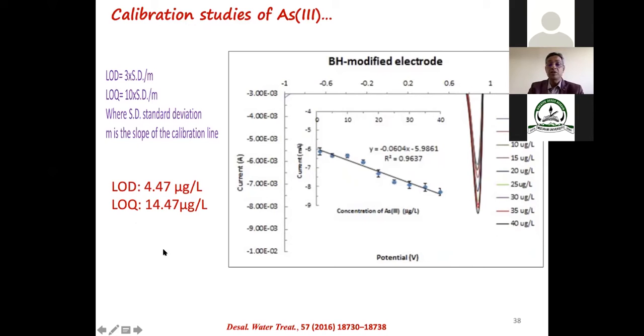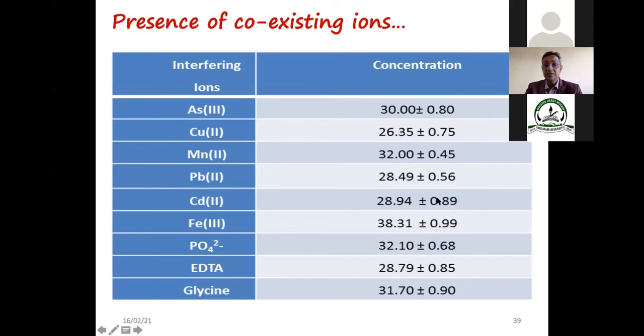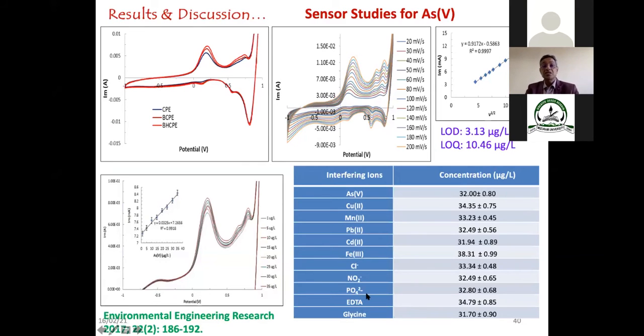The LOQ, limit of quantification, is 10 times SD by M, so 14.47. And for the other existing ions, we observed that most of them do not affect the measurement, but some ions, for example iron, did. Copper was giving some problem because the peaks come in almost the same region, the oxidation-reduction peak, especially for arsenic 3 and copper. That's why many studies have also observed that copper interferes there. So this is the sensor study which was published in Environmental Engineering Research.